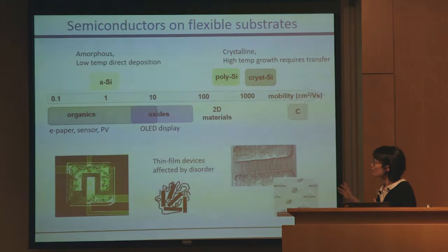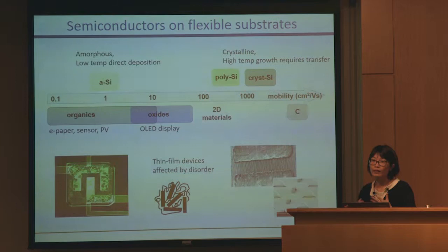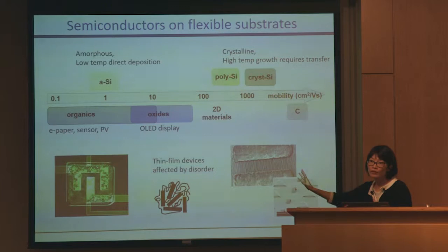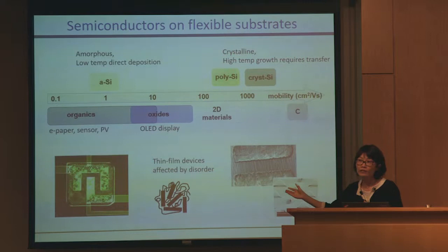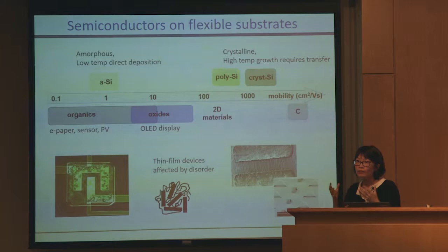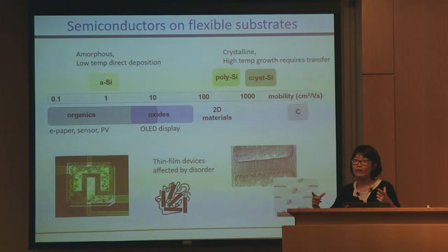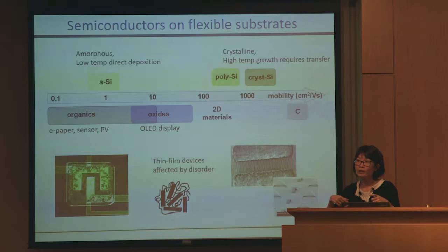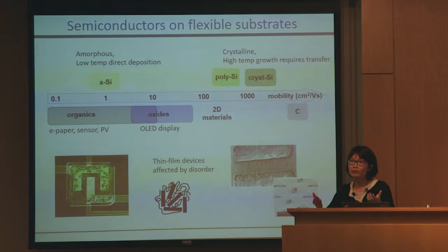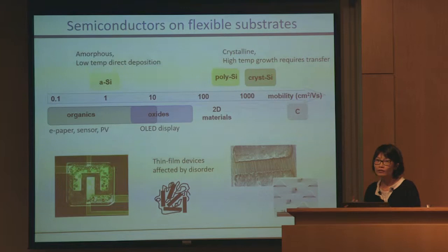And so there's also another approach where people directly deposit active electronic material onto the flexible surface. And in fact, this is not that new. It was done 20 years ago. That's the amorphous silicon material that you use every day in your laptop, in your cell phone. It's just not economical to grow a single crystal silicon to the size of your laptop. And so people found an alternative way to deposit thin film amorphous silicon, and with that, it revolutionized our mobile computing. Otherwise, we would still be carrying our chunky CRT tubes everywhere. So that is really important.